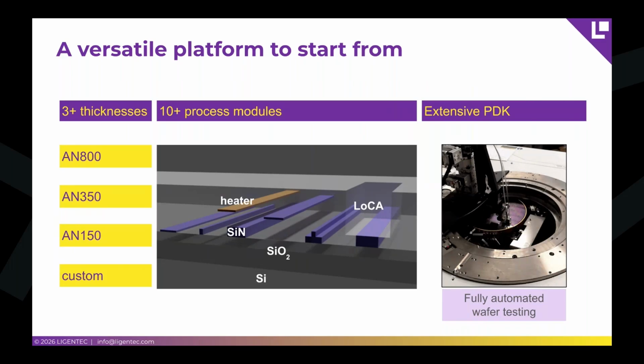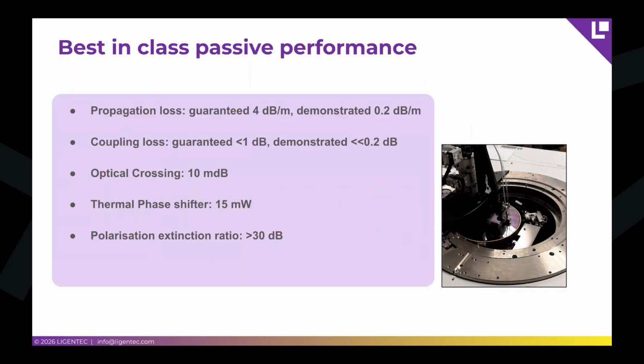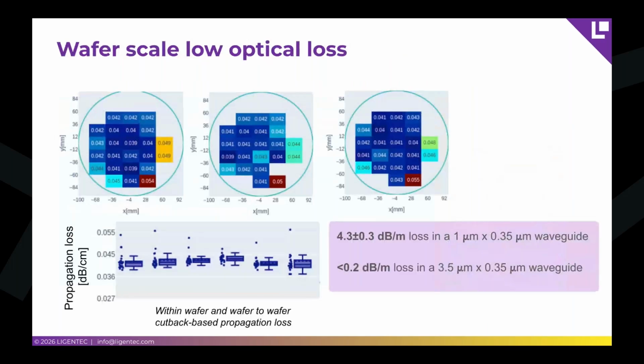That is all established within a process design kit, where we do full automated wafer testing to get statistics of the different components. So we have propagation losses that can go down to 0.2 dB per meter, coupling losses that are below 1 dB per fiber to chip coupling, but we have even demonstrated much below 200 millidB. Optical crossings are in the range of 10 millidB, and the thermal phase shifter 15 mW, and polarization extinction ratio above 30 dB. So these losses are obtained not on a single chip, but on a cross wafer.